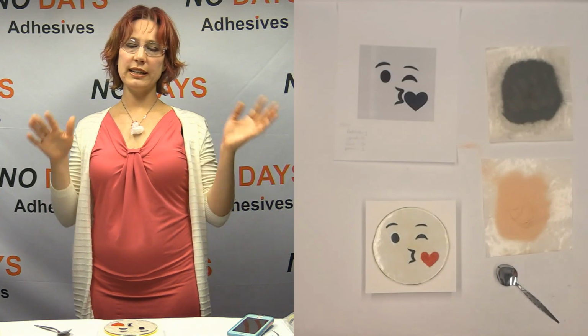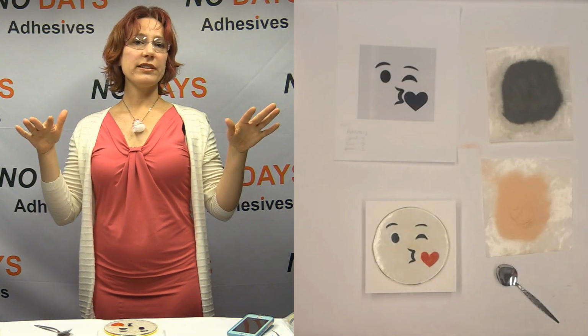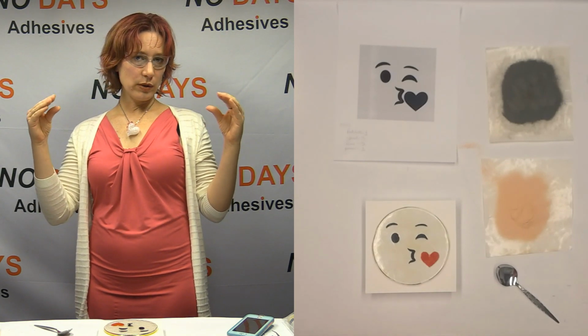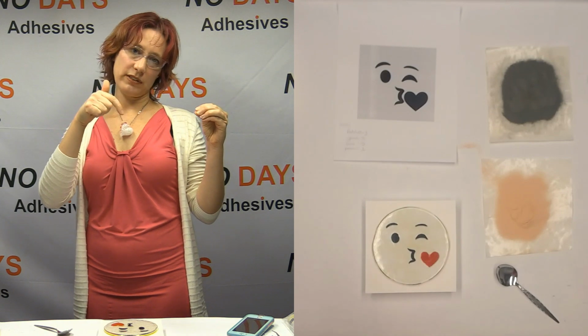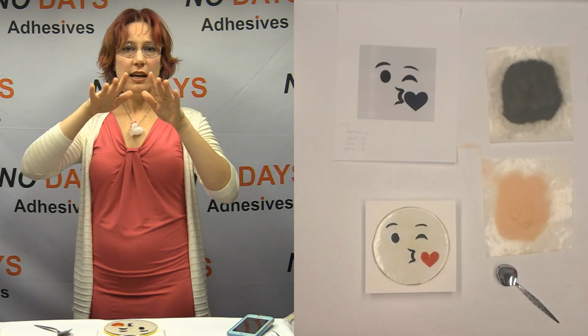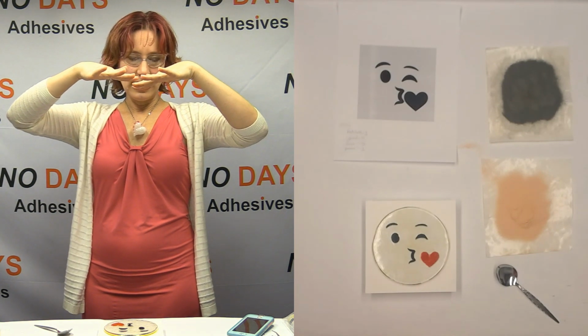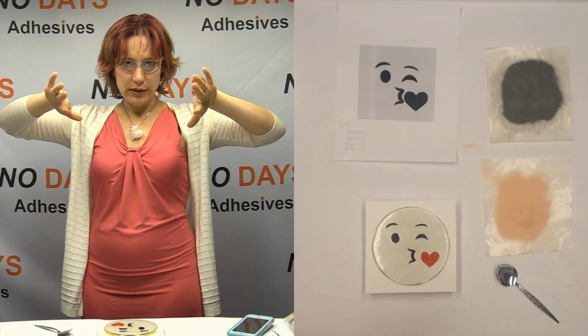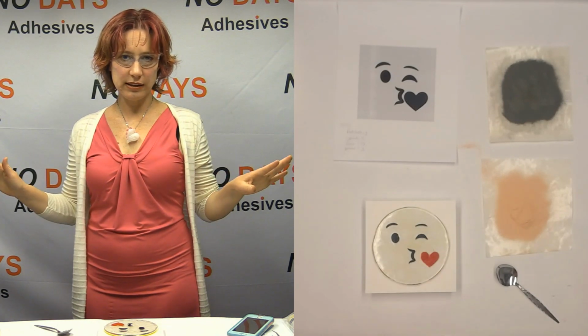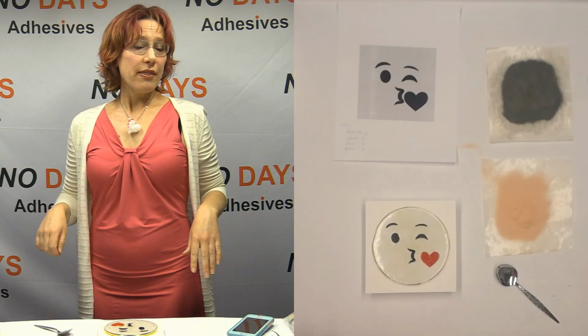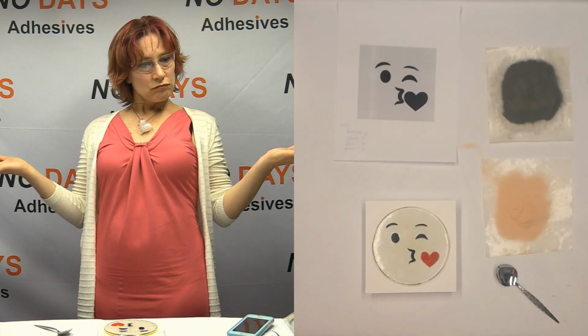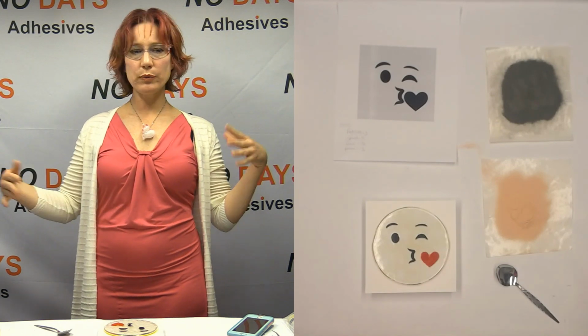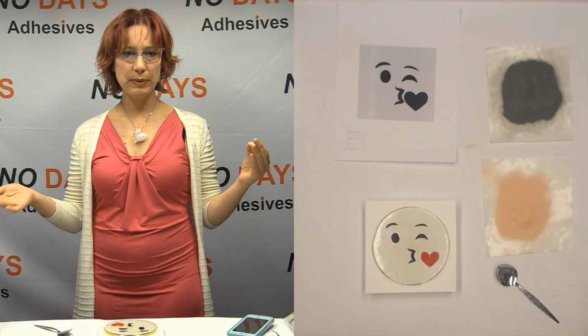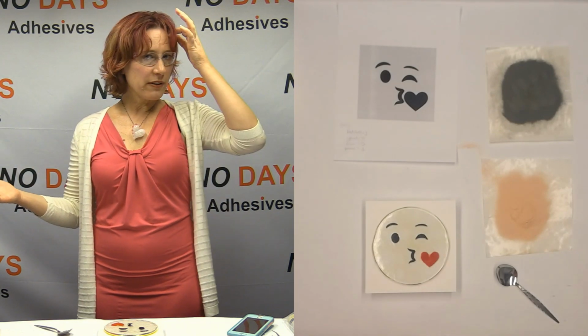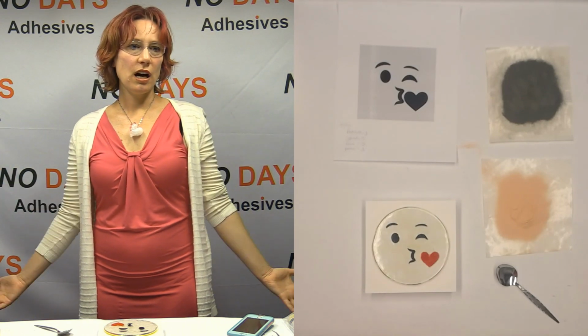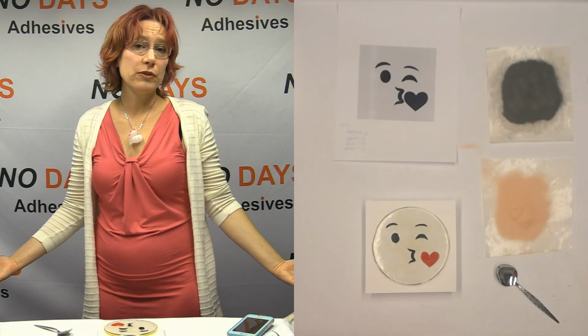So the idea behind the bubble squeeze is that it's very slowly getting everything at the same temperature so that the edges of the glass don't get uber hot and seal off before the middle of the glass has had a chance to get hot and settle in. So the middle of the glass is going to get nice and warm and express the air out to the edges before the edges seal, right? So nothing's going to melt together at 1250 yet. And then I'll probably go either 250 or 500. Once we get past that temperature, you can go a little bit faster. So it just depends on the other pieces that are in the kiln with me. But I could probably go 500 degrees up to like 1425 and hold for 20 minutes. That would be a full fuse.